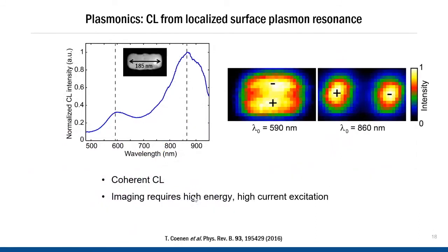And finally, this is an example from the field of plasmonics. It's a gold nanorod. Gold is a metal and it supports what are called plasmons. Now, I won't describe the experiment in detail—that will be the subject of another presentation—but what I want to point out here is that we are looking at coherent CL. So far in the examples of semiconductor material and zircons, we were looking at incoherent CL. Now, why is that important? That's because coherent CL emission is a low probability event, and so the CL signal that you can get from the sample is always low. Therefore, you need a high energy and high current for imaging plasmonic structures. So here, 30 kV beam energy and 10 nanoamps were used for this acquisition. And the main result is that we can very nicely see the two resonant peaks in the CL spectrum that correspond to the two resonance modes: the longitudinal and the transverse resonance modes.